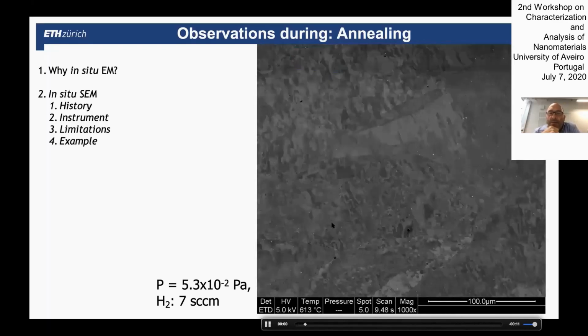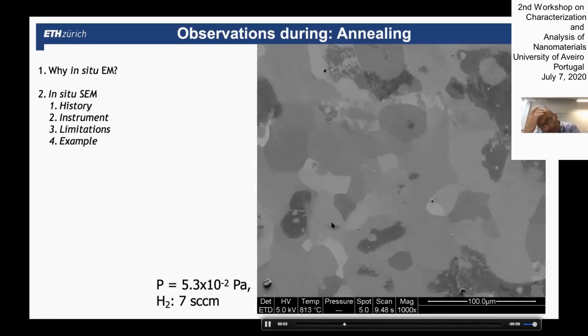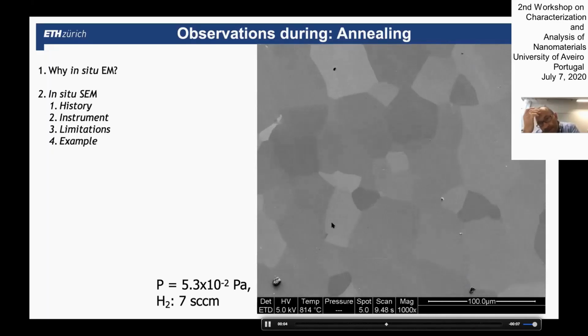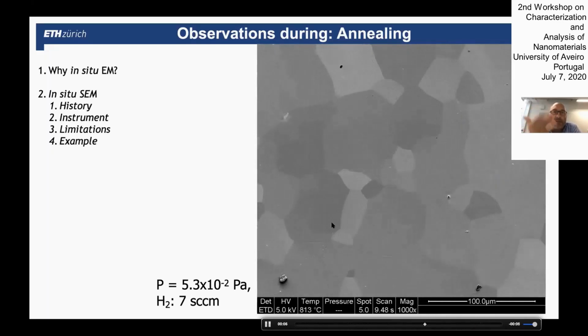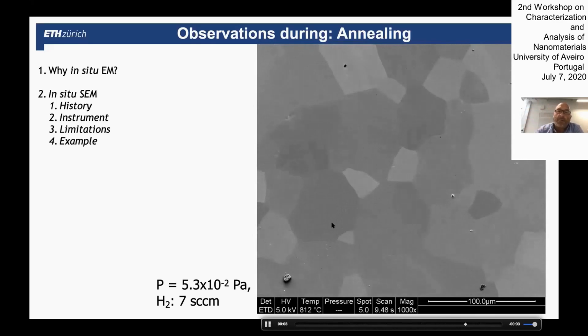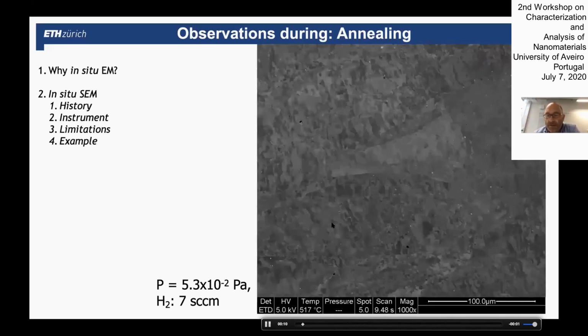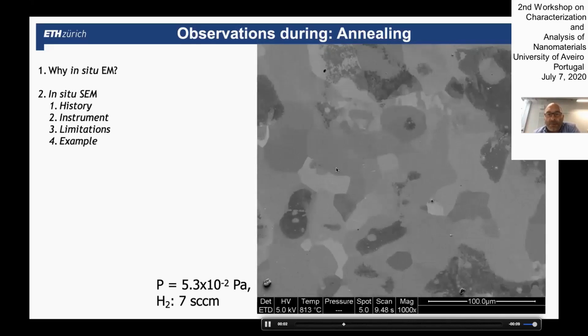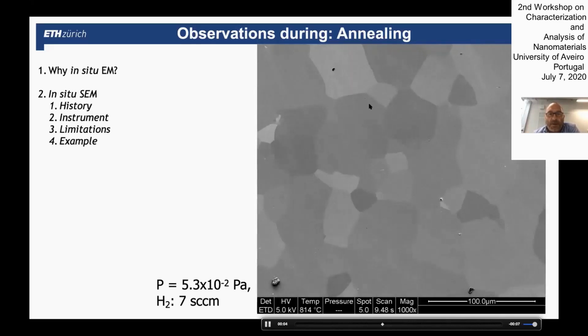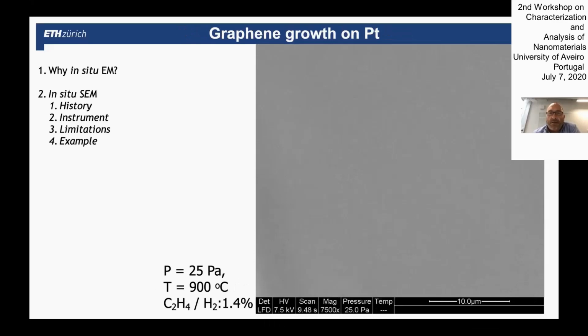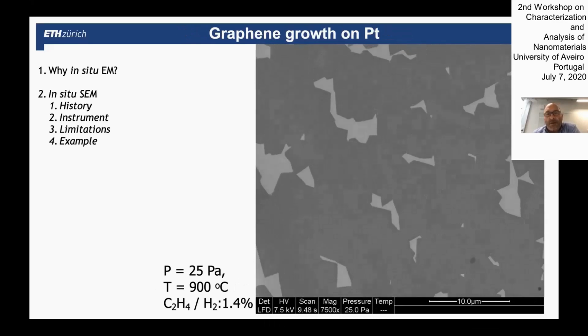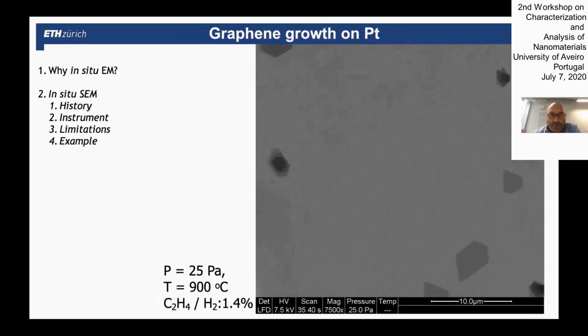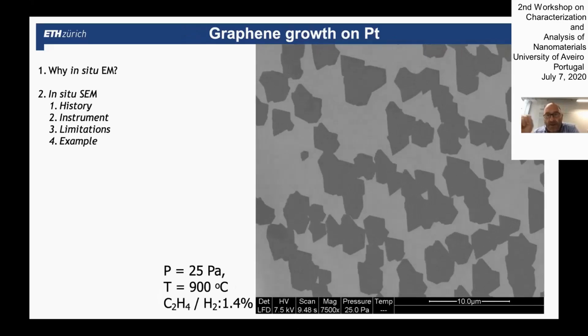We did such cleaning processes for many hours, cycling the temperature and the gas phase composition to get rid also of dissolved carbon that comes from the bulk to the surface during the annealing treatment. Once we have a clean surface, we can zoom in on any grain that we like and introduce hydrocarbon and hydrogen. Hydrogen was always there during annealing, but then we introduced ethylene in this case.